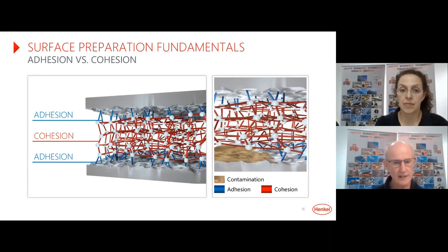So when you look at a failed adhesive joint, you need to examine the joint carefully. If it's come clean away from one of the surfaces, that's known as adhesive failure. If there's adhesive on both surfaces, then that's cohesive failure. And so if you have cohesive failure, then you need an adhesive which is stronger. And Julie will be talking about the different types of adhesive we have. We have some adhesives which are very, very strong, and some which are somewhat weaker. But there are reasons why we would do that, and Julie will go into that a bit later on.